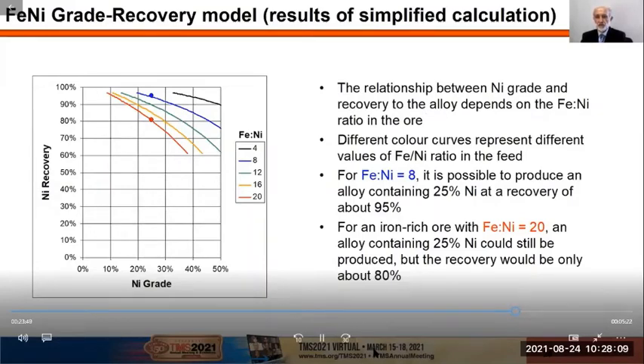The relationship between nickel grade and recovery to the alloy depends on the iron to nickel ratio in the ore, and different color curves represent different values of this ratio in the feed. So the blue curve, indicating iron to nickel of 8, we can see that it is possible to produce an alloy containing 25% nickel at a recovery of about 95%.